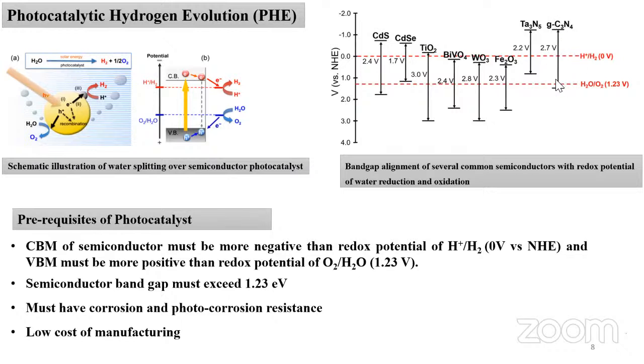One more is graphitic carbon nitride, which is a carbon material again. So such kinds of material you have to choose. The other materials which have unsuitable band edge positions might not be useful for this photocatalytic hydrogen production. I will not say water splitting, but hydrogen production. Then the second prerequisite is that the semiconductor band gap must exceed 1.23 electron volt. This is the theoretical value, so it should be more than 1.23 electron volt. They must have corrosion and photocorrosion resistance, and obviously low cost of manufacturing should be there.